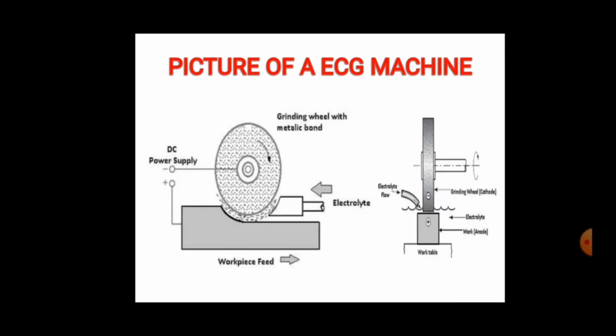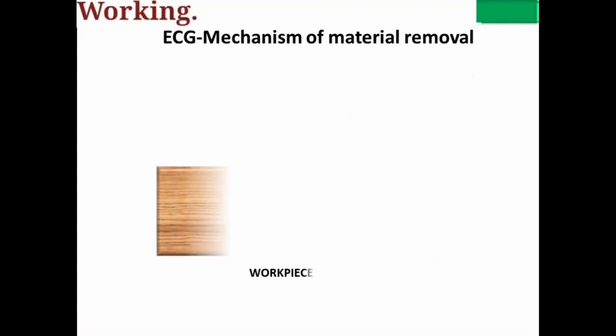Material removal in zone 1 is purely due to electrochemical dissolution, which occurs at the leading edge of the wheel. In zone 2, abrasive particles remove material in the form of chips and also remove the non-reactive oxide layer, which promotes more electrolytic dissolution. And in zone 3, where the wheel lifts off the workpiece, scratches or burrs are removed by electrochemical dissolution only.